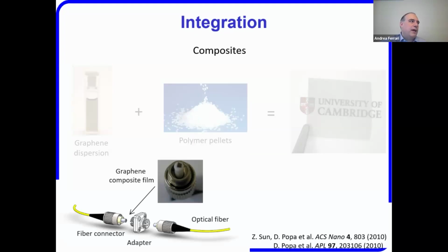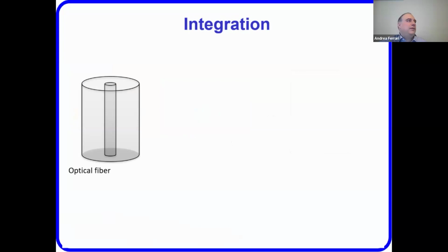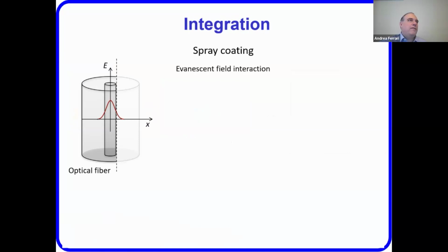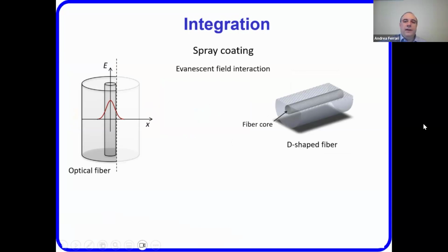So that's the top of the optical fiber. You see a small piece of graphene put there, and then it's put into a connector. Another option: you take your optical fiber, and instead of interacting directly at the top, you can interact at the side via an evanescent wave. You cut the fiber in a D shape to have the evanescent field interaction, and you spray coat graphene on top of this, and then graphene will interact with the light along the length of the fiber by evanescent field interaction.